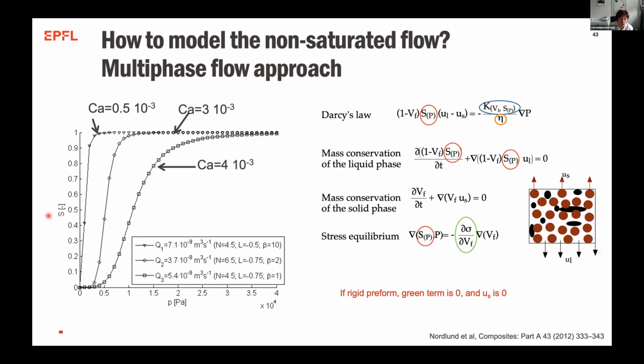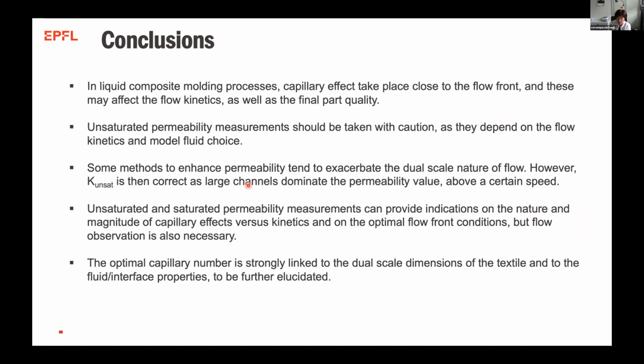And we measured saturation curve, which we extrapolated from these flow measurements. And we saw that depending on the capillary number, the saturation curve is actually different, which means that the capillary effects are different depending on the velocity as we suspected. So I will stop here because otherwise I can go on for hours on these topics.